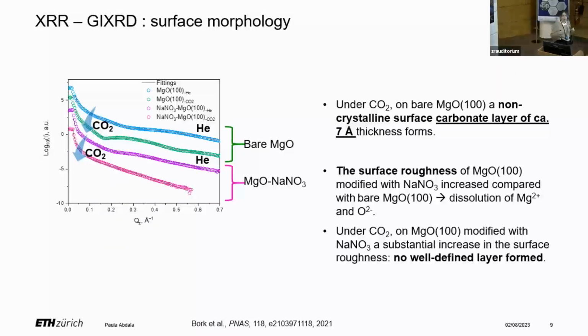Here, briefly, what are the key observations from X-ray reflectometry? The experiment was done in the following way. We first cleaned the surface with helium, and then we passed carbon dioxide and observed the change. When magnesium oxide is not modified, so there is bare magnesium oxide, we can observe the formation of a well-defined layer on the surface. When we look at diffraction, this does not give any peak. So this is a really below 1 nanometer layer that is non-crystalline on the magnesium oxide.